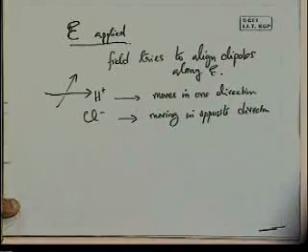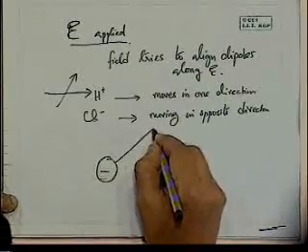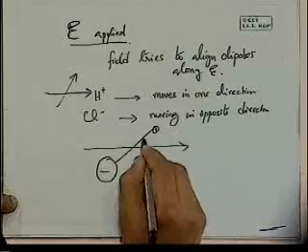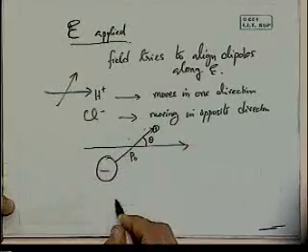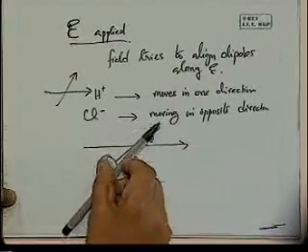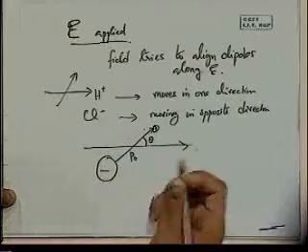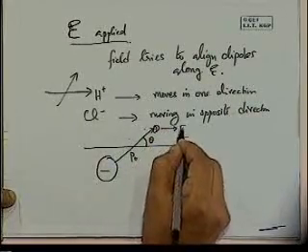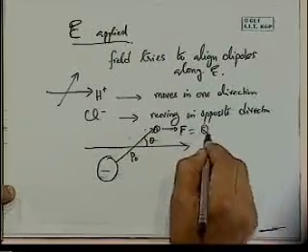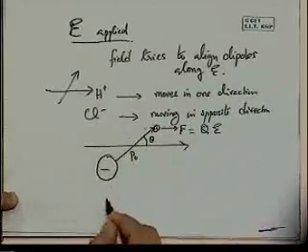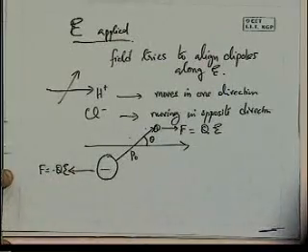Okay. So in the specific case that we will consider, I won't go into the full derivation of it. We've got this aligned at some angle theta with respect to the field. So the dipole moment built in is P naught between the negative and the positive ion, and the particular dipole moment is sitting at some angle theta to the field. And so what the field is going to try to do is to move this in this direction, where the force acting in this direction is simply charge times the field, and this one will be moved in this direction where you've got the opposite force.